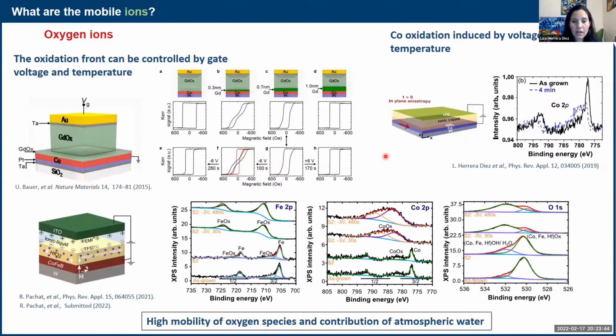And here is one of our recent measurements on cobalt iron boron hafnium oxide on tungsten. Here you can see once again the oxidation of the iron, the oxidation of the cobalt. But in particular, we can see very well the evolution of the oxygen edge. So we have a large peak at the beginning of oxygen, which of course is there because there is already oxygen in the system, so we have hafnium oxide. But at some point when we start applying the voltage, we see that the second peak at higher binding energies grows with the electric field applied. So the nice thing about this is that we were able to identify which were the oxygens that were being driven in and out by the electric field. So we could really see the signature of the mobile oxygen. They had a different electrochemical environment from the oxygen from the hafnium oxide.